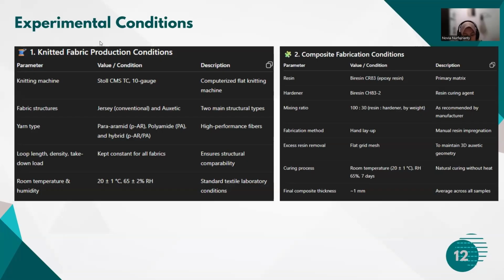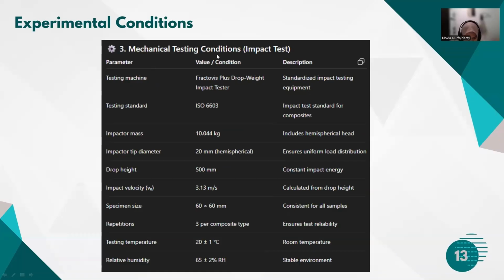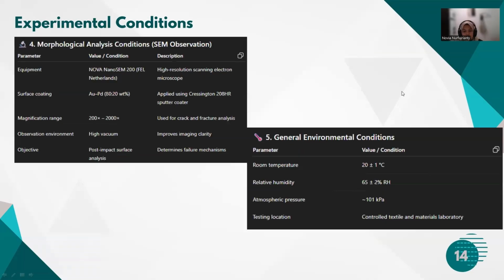Experimental conditions. The experimental conditions are presented in the table below. Knit fabric production conditions and composite fabrication conditions: the fabrication method is the hand layup method. And the mechanical testing condition: using a drop impact test following ISO, and the impactor mass is 10.044 kilograms. And the morphological analysis condition is using SEM, using a Nova NanoSEM, and for general environmental conditions.